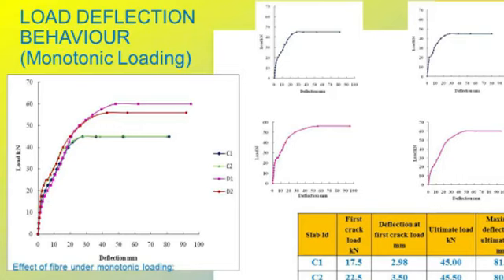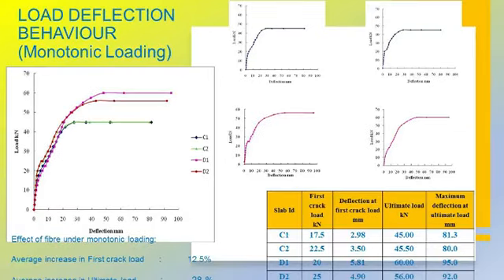And there was an average increase in first crack load in the case of slabs with fiber. The average increase in first crack load was 12.5%, and the average increase in ultimate load was 28%. So these are the first crack load readings and the deflection readings observed in these slabs without fiber and slabs with fiber.